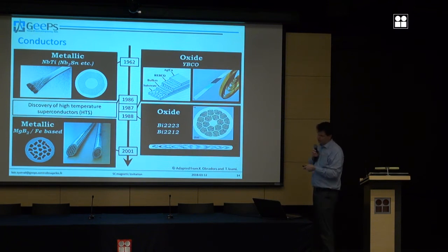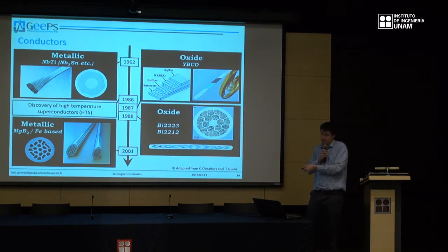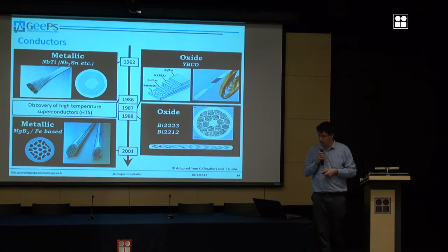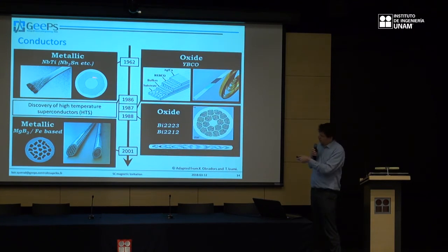And recently, in 2001, a Japanese team discovered the material MgB2, and they could manufacture conductors quite quickly, it's been only 15 years, okay? And it's commercially available already in kilometer lengths. So it's something interesting. This one and this one operate at quite low temperature. This one is less than 9 Kelvin, this one less than 39 Kelvin. So it's quite cold, but they will probably be used for the same kind of application. This one is at higher temperature, around 100 Kelvin. So it's a little bit easier to use, okay?